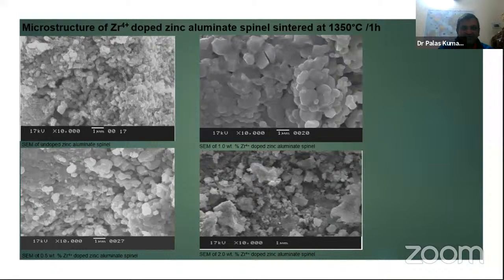Here, the zirconia-doped zinc aluminum spinel microstructure has been displayed. Extreme left is the undoped, then 0.5%, 1%, and 2%. It is very clear that with increasing dopant concentration, the grain size distribution gradually increases, especially up to 1% zirconia concentration, and after that there is something different. Up to 1% zirconia dopant, the microstructure is orderly maintained.